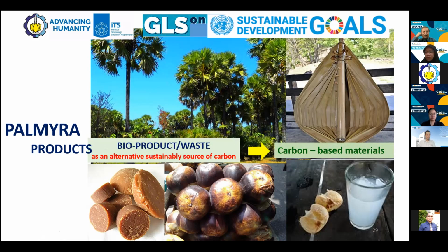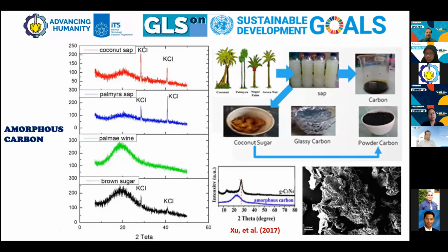So this bioproduct or waste can be converted into carbon-based material. The result of carbonization, the biochar, has an amorphous phase according to the XRD spectra. The starting materials used here, you can see, are the coconut sap, the Palmyra sap, palmae wine, and also brown sugar. All samples show almost the same pattern of XRD spectra, and this is the impurity phase coming from the product, which is very commonly detected in the palm family. And we can make it disappear by rinsing with water, and it's like this one. There's no peak of potassium chloride here.